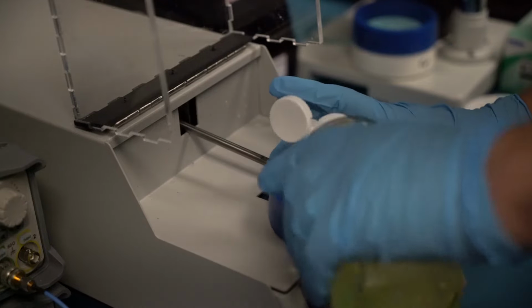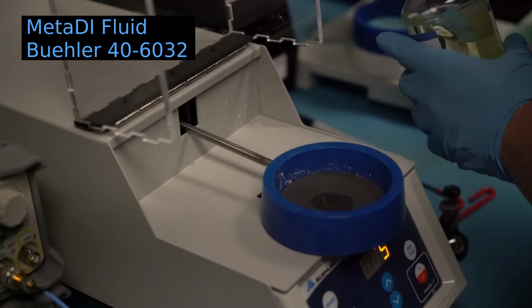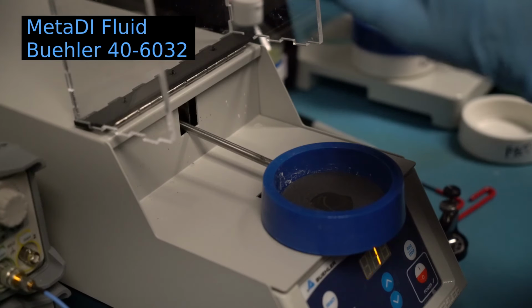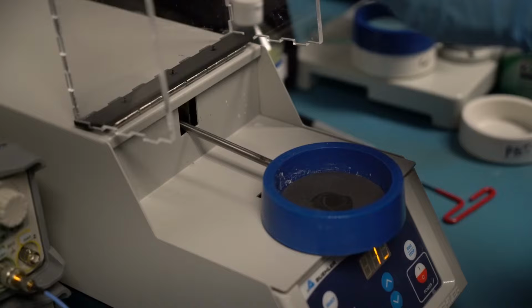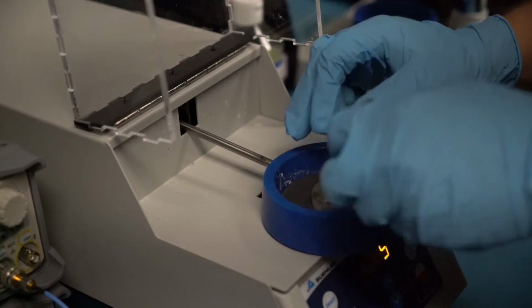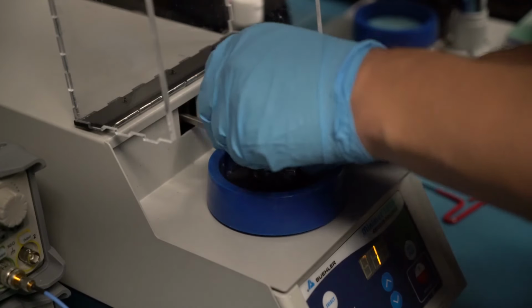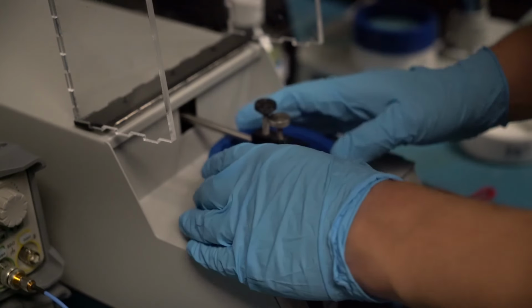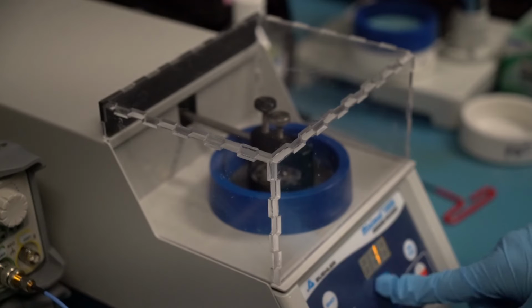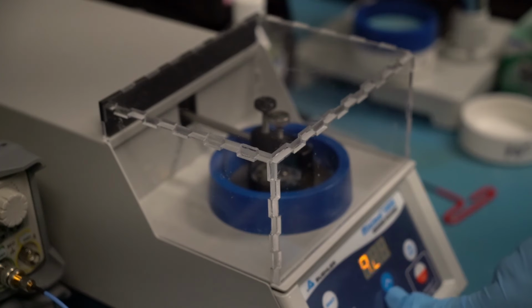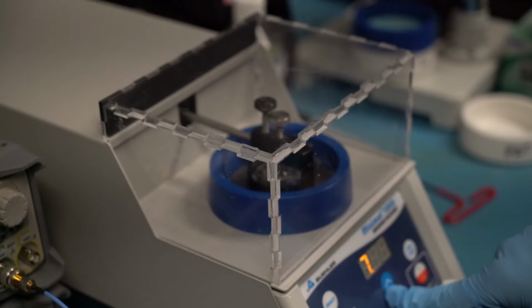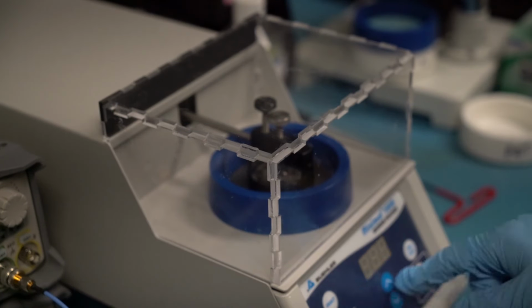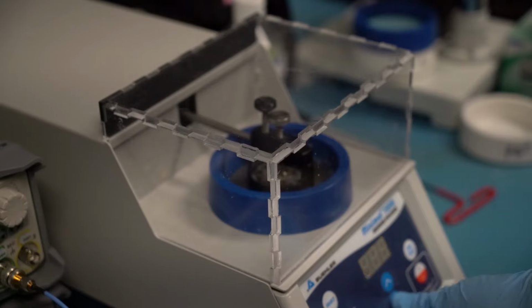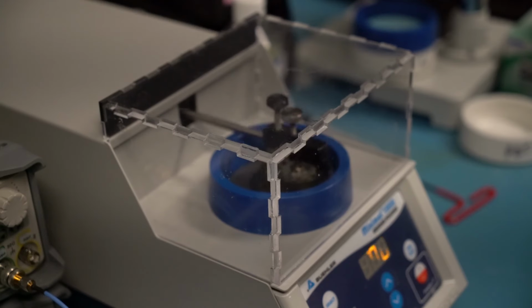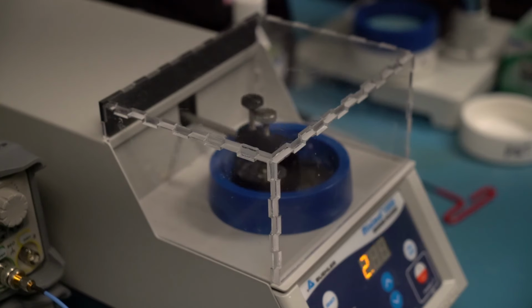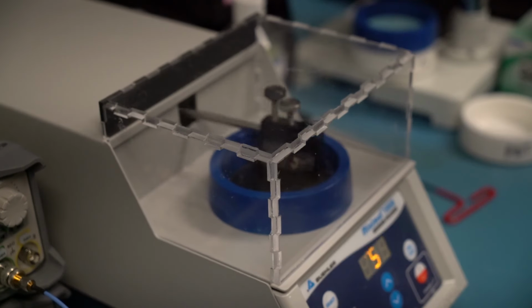Just get a little bit of lubricant on here so we don't have too much dust and it doesn't overheat. And get it mounted up in the fixture. For the first pass, I'm only doing 2 minutes. There are going to be several more passes off camera. With the silicon carbide papers on this polisher, you do want to limit the duration of a single polishing pass to around 2 minutes. If you go too much longer, then you start getting uneven wear and the surface becomes very non-uniform.